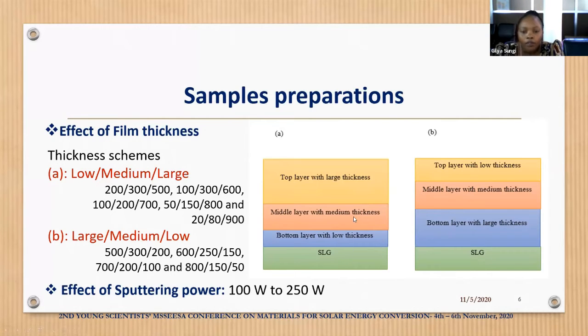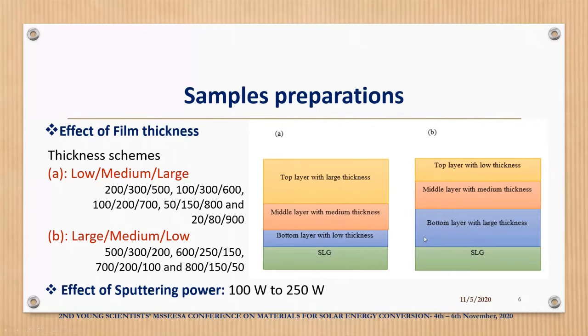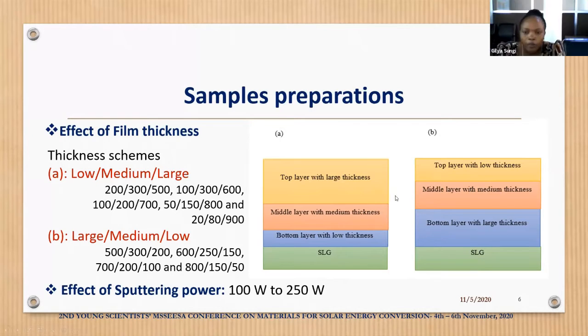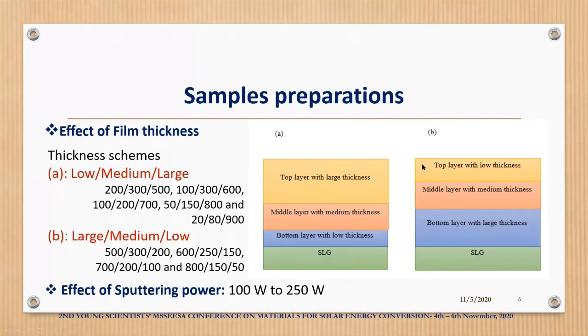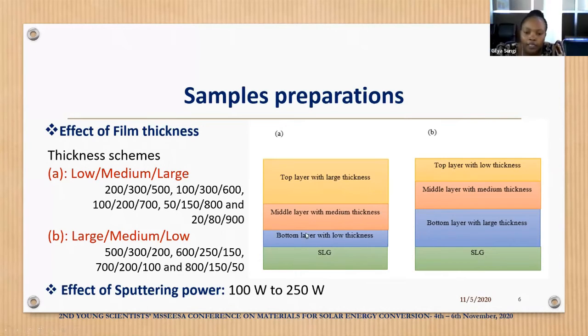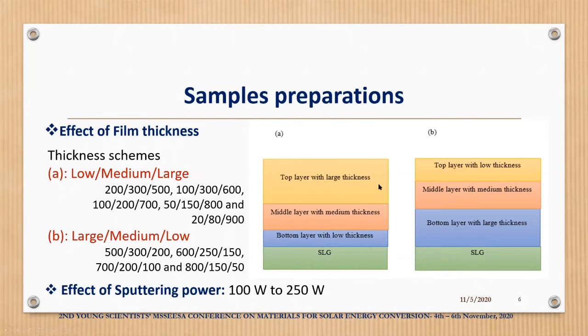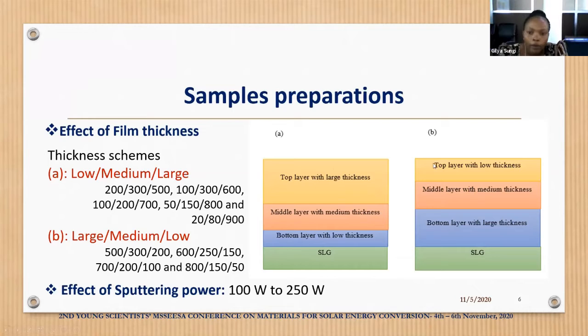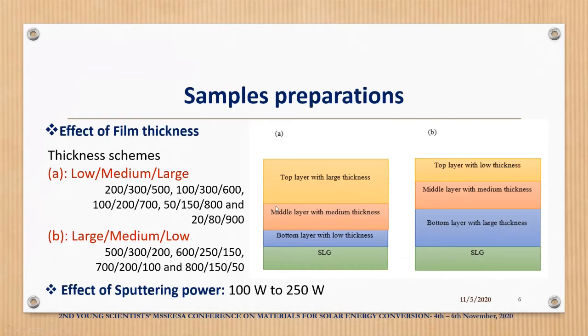And remember, all these layers show different colors, which implies that each layer will be deposited with different parameters, such as working gas pressure, whereby the bottom layer will be deposited at high working gas pressure, because at high working gas pressure, we're going to have a film with porous microstructure, but with better adhesion. And the middle layer will be deposited at medium working gas pressure, whereby the top layer will be deposited at low working gas pressure, whereby you're going to get compact microstructure with a low resistivity, which will give higher conductivity.